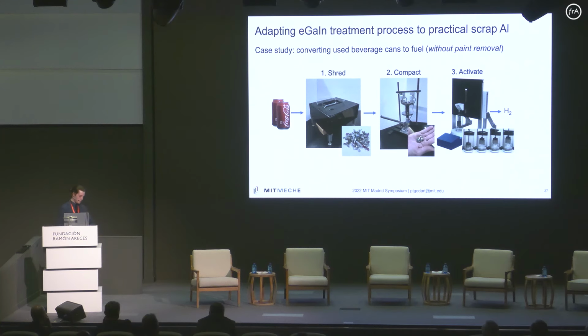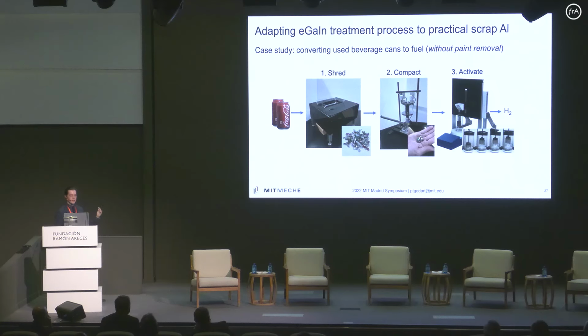So moving on from there, I took this technology and wanted to apply it to actual practical scrap aluminum. So we knew that this worked with our 99.999% pure aluminum ball bearings, but how did this fare when we threw in other contaminants, particularly surface contaminants like paint on the surface of a soda can, for example? And we wanted to do this without having to remove the paint specifically. And so we chose soda cans as a very difficult case study for converting aluminum scrap.